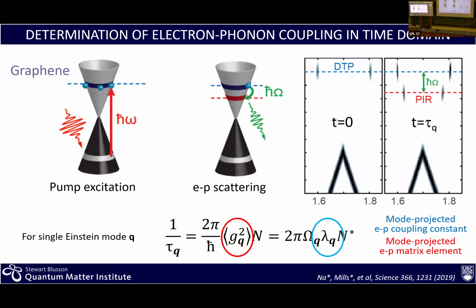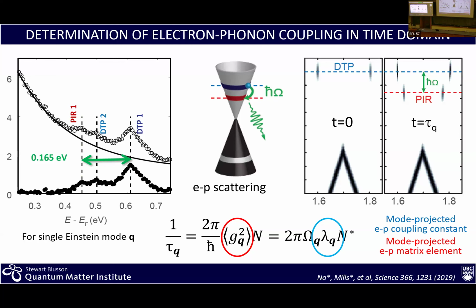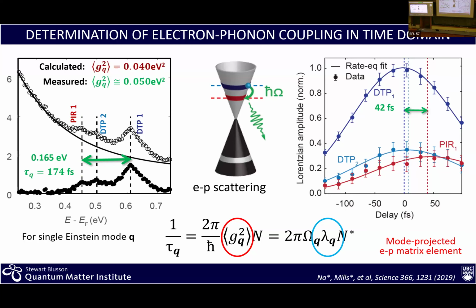Okay, so the idea is to look at the integrated intensity of these peaks and see how it changes with time. So basically, this is the result of the process of a single electron scattering with a single phonon. So that's a population lifetime. What you get out of that, and again, we have two scattering processes that we include. One is the electron-electron, and the other one is electron-phonon. And then by doing the full analysis of these intensities, the lines that you see going through are not guides to the eye. They are really the result of a rate equation fit to the overall spectrum over time.